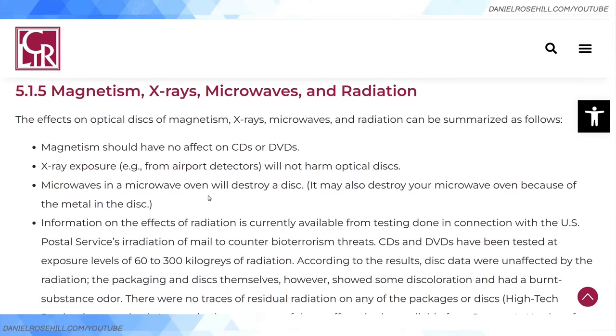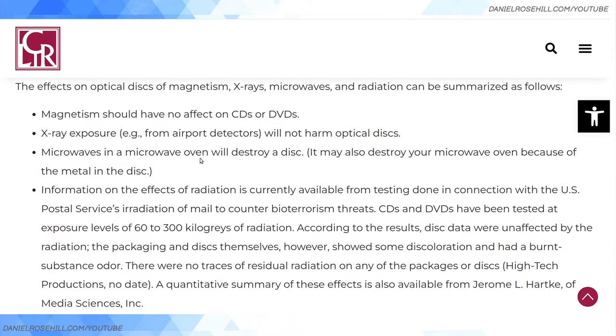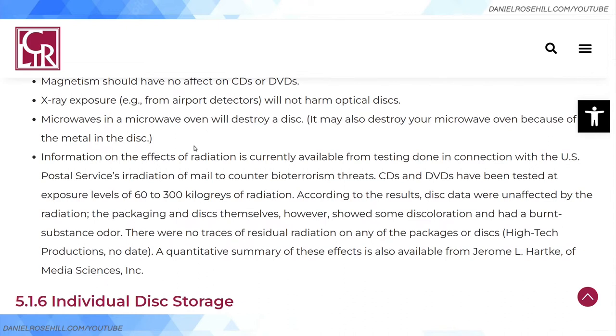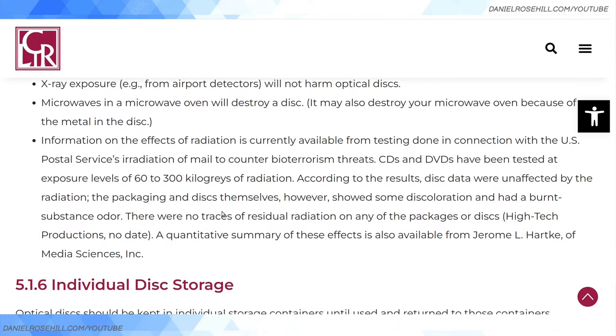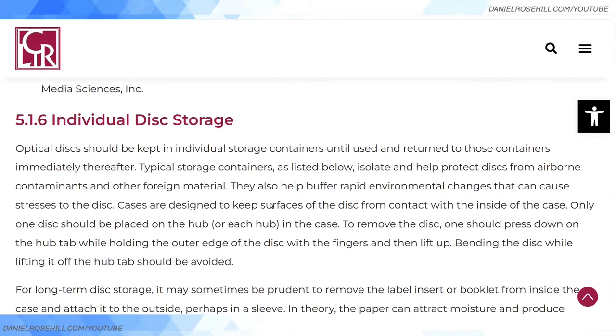A few more tidbits: magnetism shouldn't affect CDs and DVDs, so X-ray exposure should be okay. Don't put them in a microwave though — that will destroy the disc. Regarding mailing your M-Discs: the US Postal Service and most postal services scan packages to counter bioterrorism threats. Testing at exposure levels of 60 to 300 kilogreys of radiation found that discs were unaffected, with no traces of residual radiation. So don't worry about your M-Discs being scanned in transit.